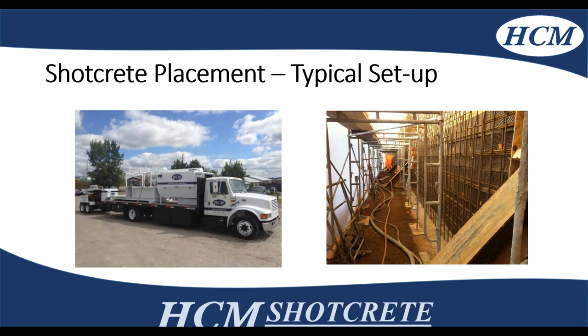Now I'm going to run through a typical setup for a wet mix condo foundation wall. On the left, we have our typical setup — we drive on site with our equipment: a tow-behind pump, a 375 compressor, and a tow with all our hoses, small tools, and scaffolding. On the right-hand side, you can see the setup with scaffolding and hose laid out, prepped for a shoot. This is a 300mm wall with a double mat of 15M rebar on 300 centers, both horizontal and vertical, hoarded because we're shooting this in winter to keep the proper ambient and substrate temperature.